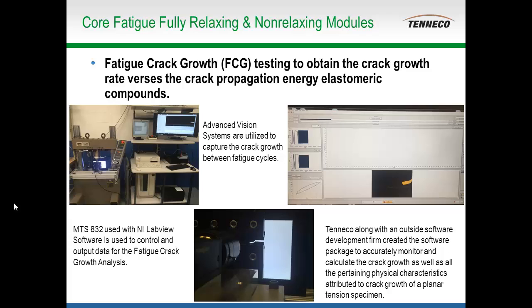The basic test procedure, you start at a very small strain level and you ramp that strain in very short time increments, 1 or 2, maybe 5 minutes. And over a 20 to 24 hour test period, that strain is continually increased. So you get 3 to 4 decades of crack growth rate versus energy release rate.